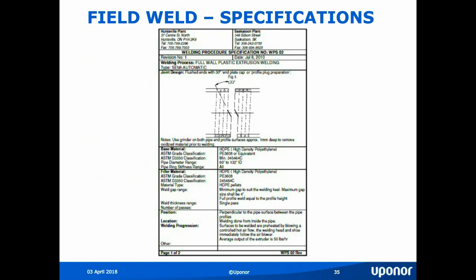If you are designing a Weholite piping system for your power project and want to get specific on the welding of the pipe, then we have these specifications that you may use in order to specify the type of weld you would like to see on your project. That's pressure dependent. Up to 7.5 psi would be just an ID weld, and beyond that, we can use the internal welder or an ID and OD weld. But for most projects, they don't get that specific. Just by stipulating the pressure and extrusion welding, that would be enough for a manufacturer to base their welding estimate on, and for the contractor to understand what type of weld is required.